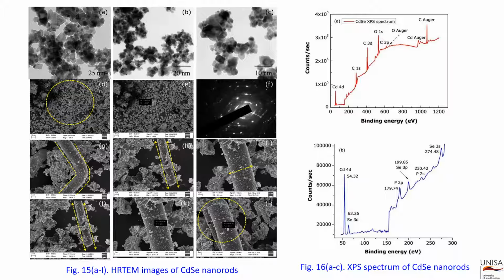The cadmium Auger is at 974.39 electron volts. The Se Auger value is at 1069 electron volts. In the general scan of our CdSe XPS spectra, we see C1s, Cd3d, O1s, Se3p, O Auger, Cd Auger, and Se Auger. The cadmium 3d peak in each case has a doublet due to the spin orbit splitting, resulting in 3d 5/2 at 404.2 electron volts and Cd 3d 3/2 at 411 electron volts, and cadmium selenide agrees well with those values. So the Cd 3d core level is satisfactory for the spin orbit pair.